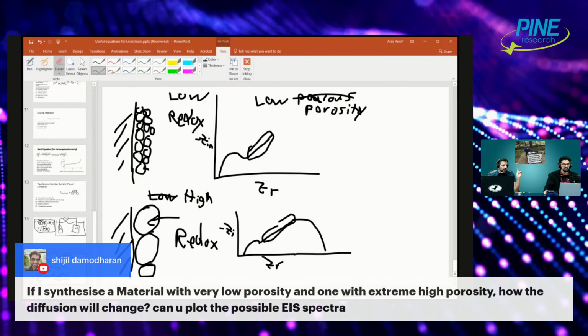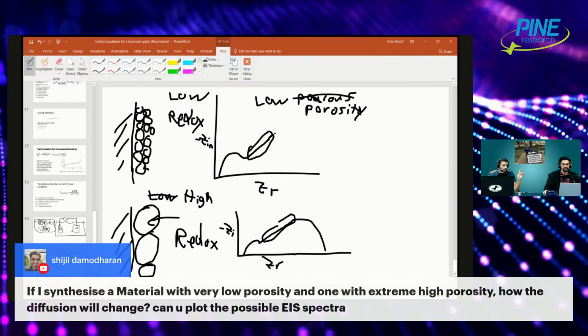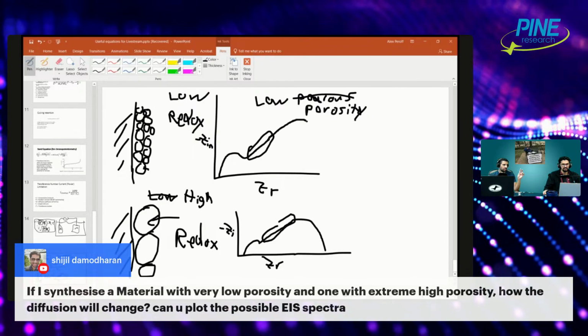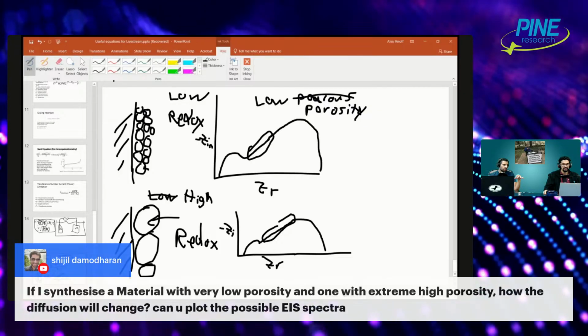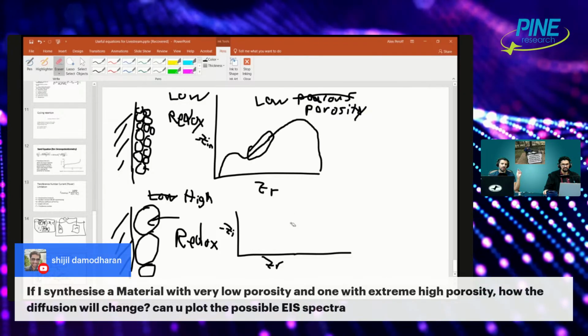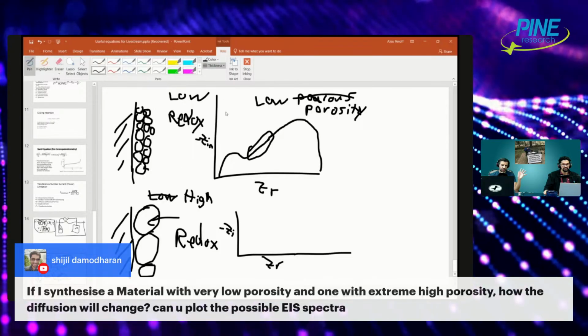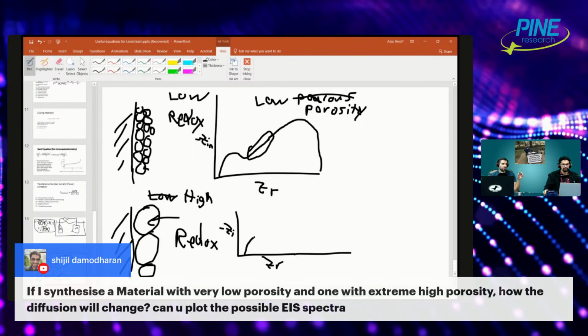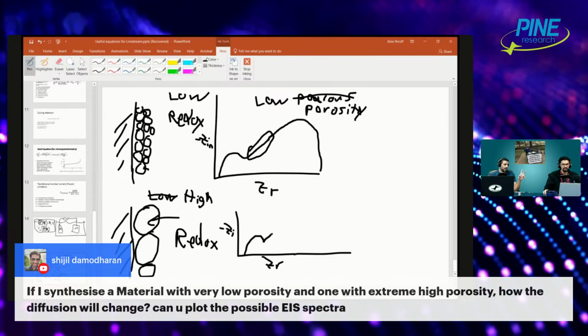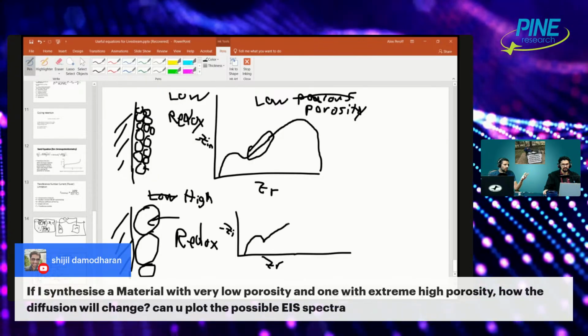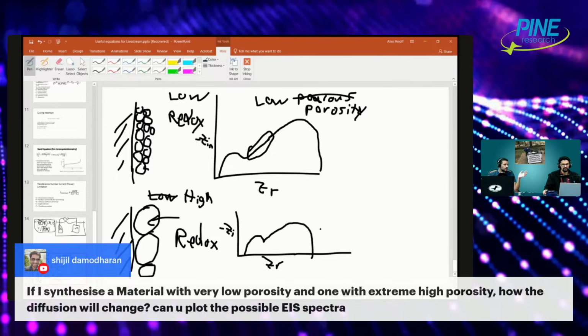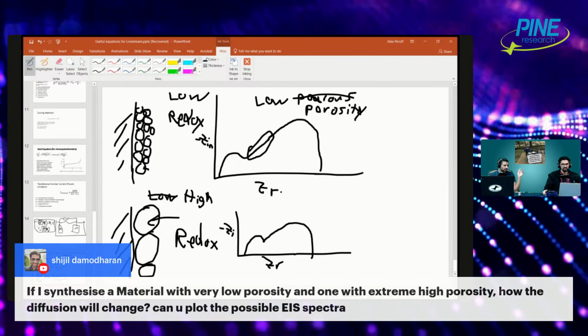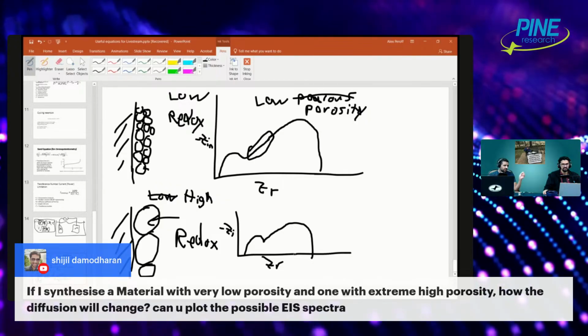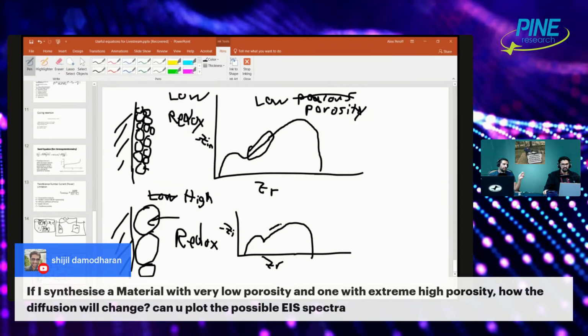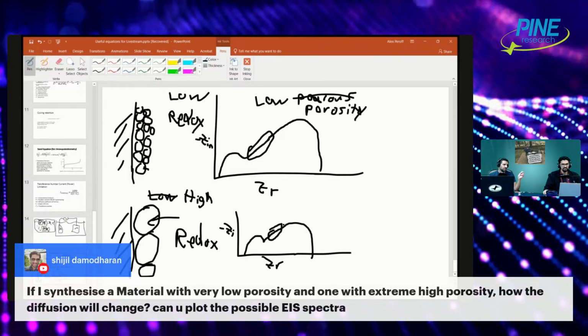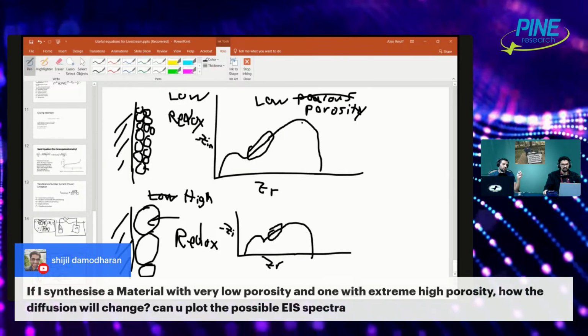Which means that the length of the 45-degree line is very long. It might still curl, it might still make a short, but there's going to be a long 45-degree line. Now on the bottom, high porosity, because the particles are large, so there's a larger volume fraction of empty space, which is electrolyte. So there's space for ions to move. Porosity is high, they can move a little more easily. The impedance is lower. The length of the 45-degree section is probably shorter. So the length here is shorter. W is smaller. So that's my guess.